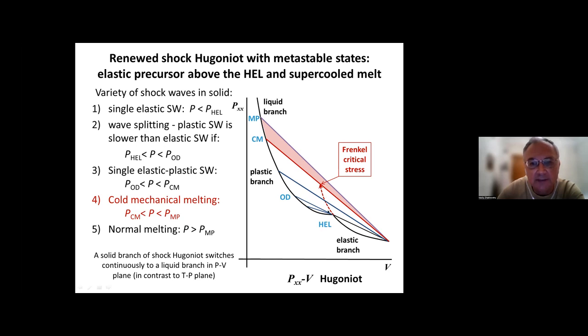When it exceeds the limit, we have a wave splitting regime. The plastic wave is slower; the slope of this Rayleigh line corresponds to the shock. The plastic shock wave is slower than the elastic precursor, so two waves can actually be observed. And above the overdriven state, the plastic branch starts where a single elastic-plastic shock wave can be observed. It's a single wave but consists of two zones, the elastic zone here until the intersection of the Rayleigh line with the elastic Hugoniot, and the plastic zone here. They have different amplitudes but the same velocity, so they propagate as a single wave.